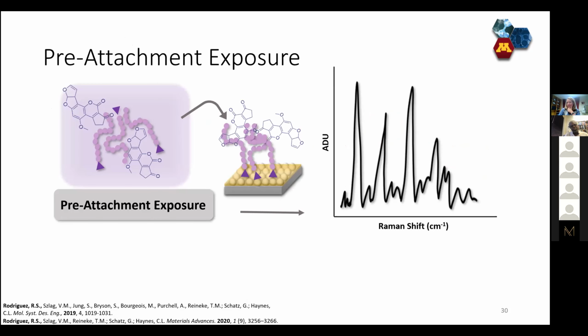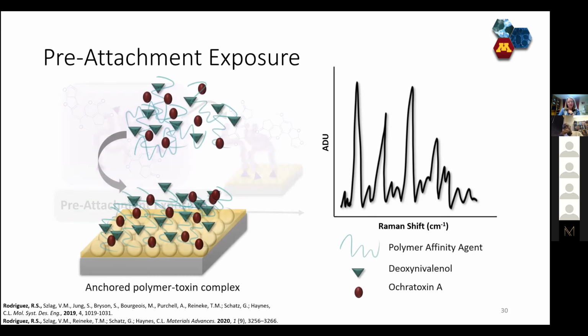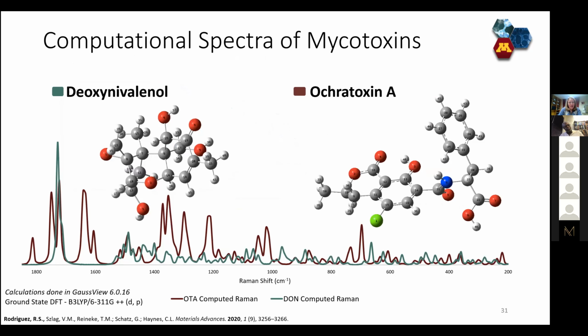So we were going to proceed kind of as you could guess we would, based on the first bit of this talk, where we were going to take our polymer, allow it to interact with our targets, and capture a Raman spectrum. But now we want the same polymer to interact with multiple targets. So in this case, the little green triangle is meant to be DON, and the little red oval is meant to be ochratoxin. And ideally, we'd get a Raman spectrum that has distinct bands for each of the different mycotoxins that are present. Because then ideally we would know both are there, we might even be able to quantify each of them separately. So that's what we're going for in this work. You might worry that the different vibrational bands or Raman active bands for the two molecules might be too similar, and maybe you wouldn't be able to tell them apart.